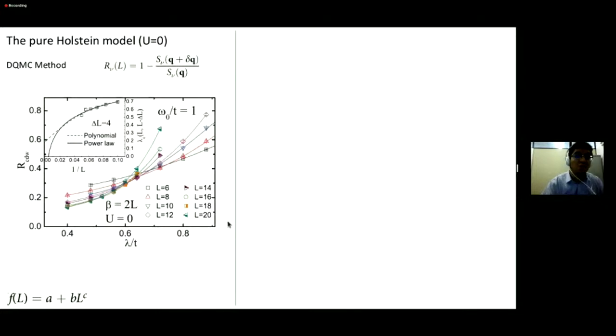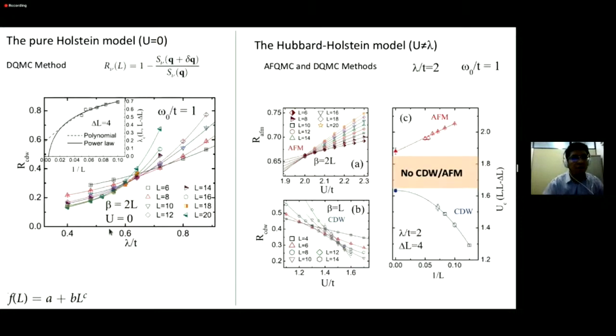So in 1D, we really need a minimum electron-phonon coupling to have CDW, while in 2D we don't need it. For any electron-phonon coupling, you have CDW formation. So we repeated this analysis of the correlation ratio for different values of lambda. Lambda here is basically the electron-phonon coupling. For different values of lambda and different values of the electron-electron interaction, we could provide the boundaries of the different phases, both CDW and antiferromagnetic phase.